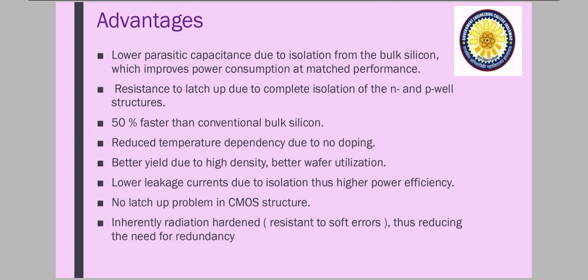The advantages of SOI: substrates of Silicon on Sapphire (SOS), oxygen-implanted silicon (SIMOX), and those made by wafer bonding all fall in the category of SOI material. Micro circuits made with these materials are more radiation resistant than those with bulk or conventional silicon, and they are less subjected to alpha particle upset, which causes soft errors. SOI also has lower parasitic capacitances due to isolation from bulk — there is no direct contact, and the insulator layer eliminates parasitic capacitance issues. This improves power consumption, and these devices are 50% faster than conventional bulk silicon.